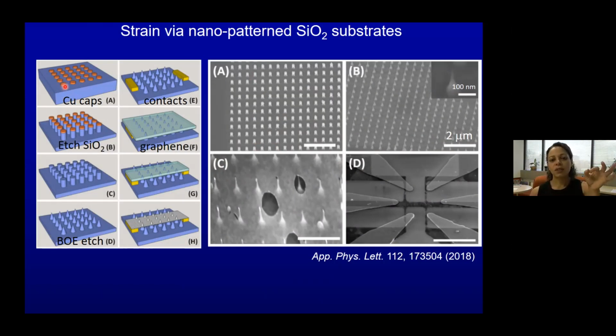And then we used those caps as a mask to etch the silicon oxide. Okay, we ended up with these pillars of silicon oxide. And you can see that here in A. This is an array of pillars of silicon oxide. The scale bar is 2 microns. Okay, and then we did a BOE etch. And what the BOE etch does is it sharpens up the silicon oxide.